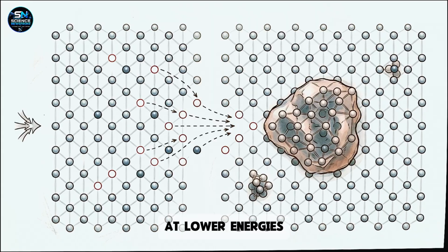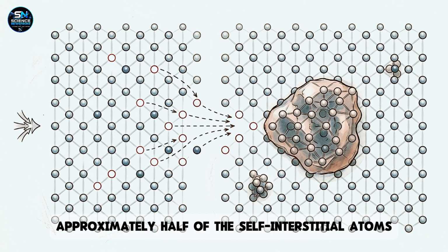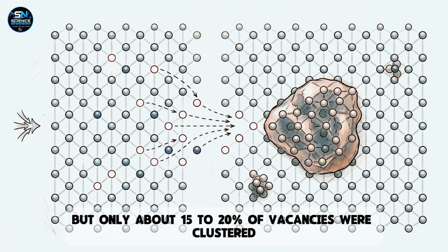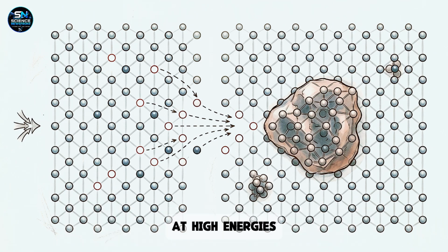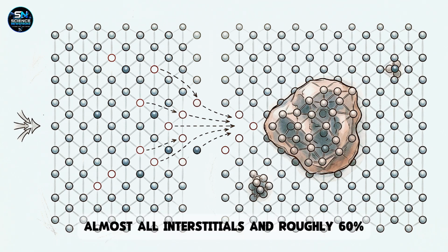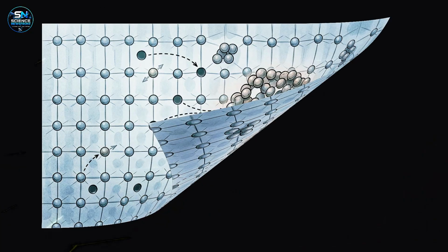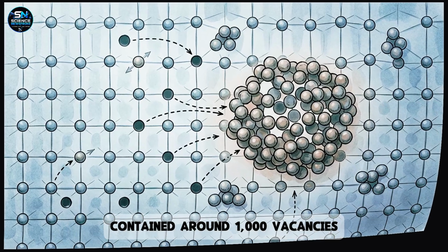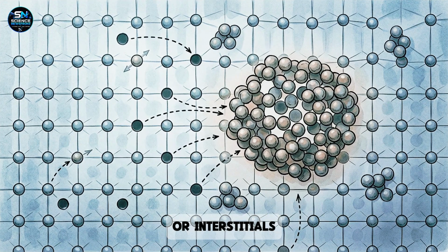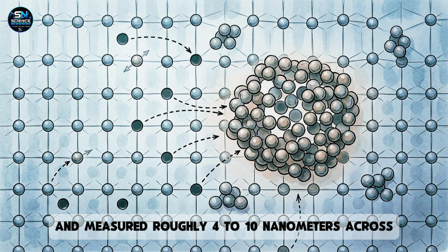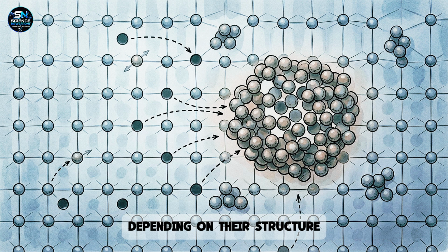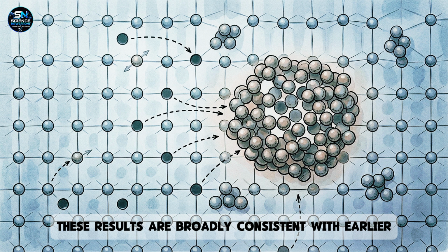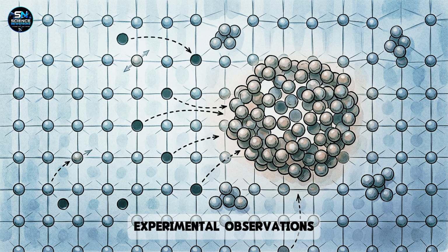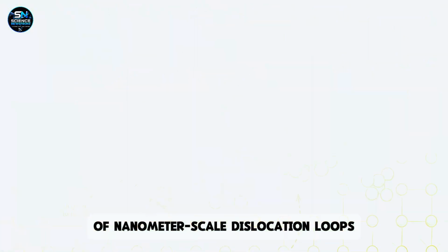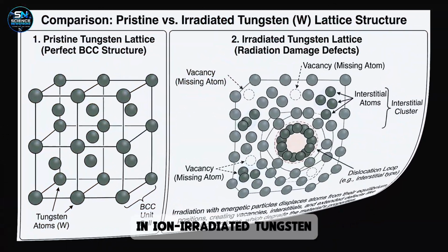At lower energies, approximately half of the self-interstitial atoms but only about 15 to 20% of vacancies were clustered. At high energies, almost all interstitials and roughly 60% of vacancies belong to clusters. The largest frequently produced clusters contained around 1,000 vacancies or interstitials and measured roughly 4 to 10 nanometers across, depending on their structure. These results are broadly consistent with earlier experimental observations of nanometer-scale dislocation loops in ion-irradiated tungsten.